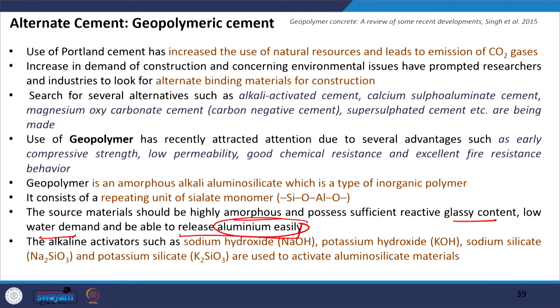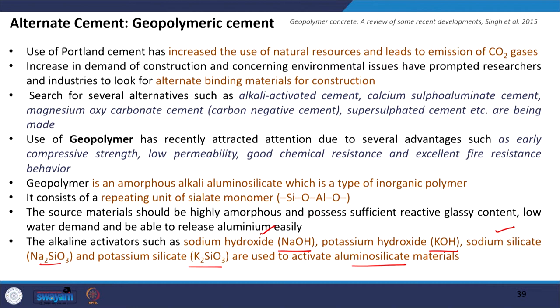The activators used to create an alkaline environment consist of several options, with common options being sodium hydroxide, potassium hydroxide, sodium silicate, and potassium silicate. These are used to activate the alumino-silicate materials such as fly ash or GGBFS. Sodium hydroxide and sodium silicate are preferred because they are able to extract aluminium more easily from the alumino-silicate material.